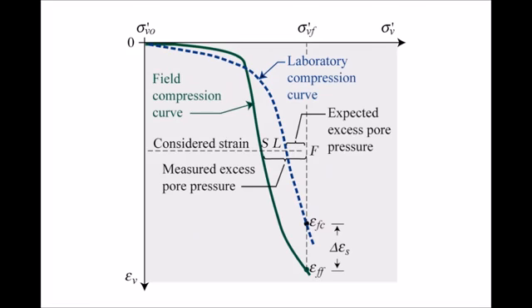Now, there are some cases where the data were not so well defined, but we can say that if we have the laboratory curve here in blue and the field curve in green, and if we estimate at a considered strain, if we estimate the pore pressure from the laboratory curve, the excess pore pressure at a given time is Fl. But in situ, it should be Fs, with Fs larger than Fl. That's in the logic of the strain rate model.